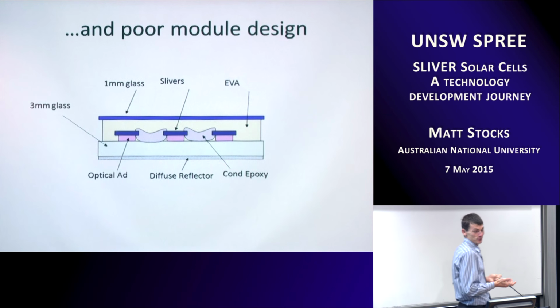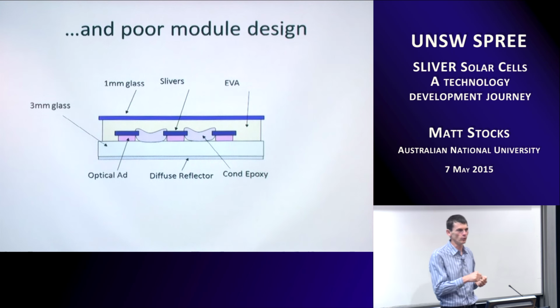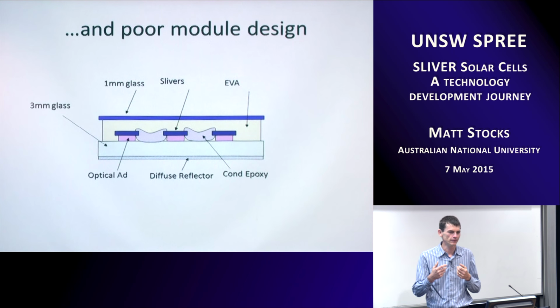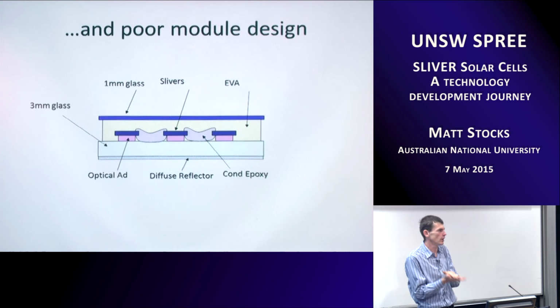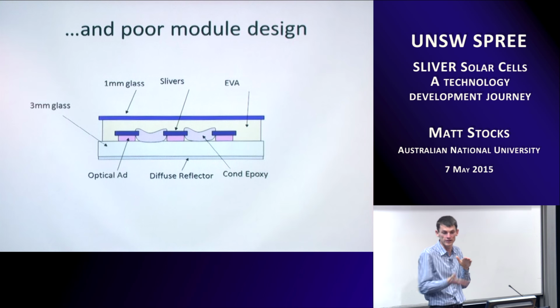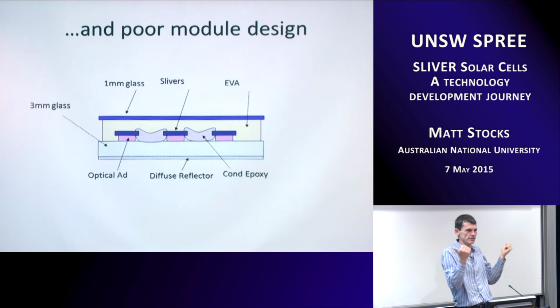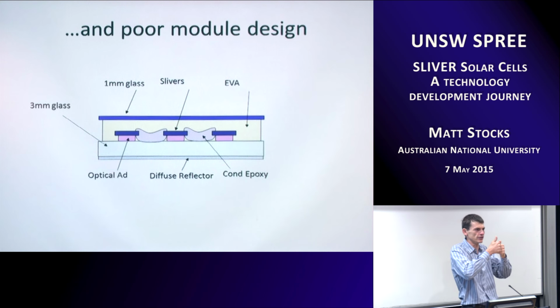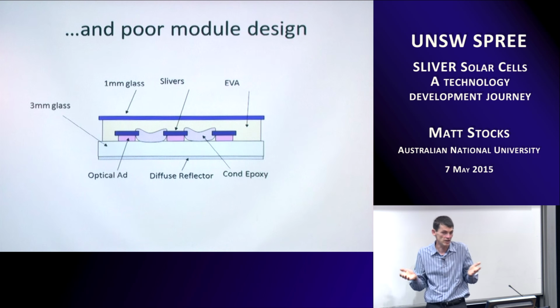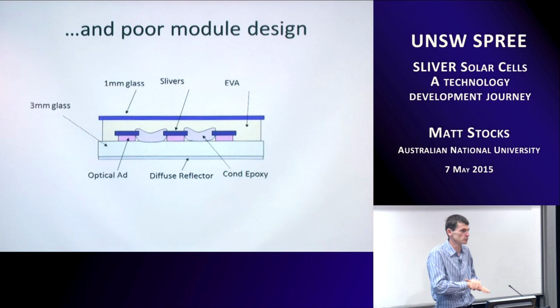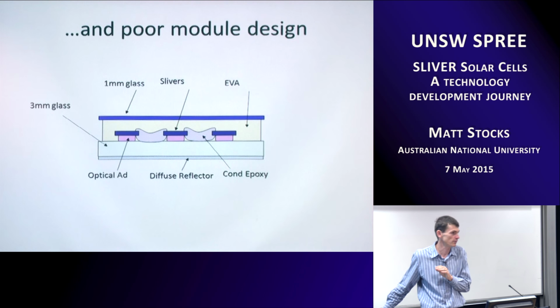We also had a really bad module design. What I talked about before was the fact that we spread the cells apart and that we wanted to get light reflected from the rear. In order to do that as efficiently as possible, we wanted that reflector to be as far back as possible, because if it was too close to the cells, it was hard for the light to get sideways. Too much of the light was just going back out the same hole that it came in. So naturally, we went, well, we can just put that on glass. We'll put that separate from the cell.